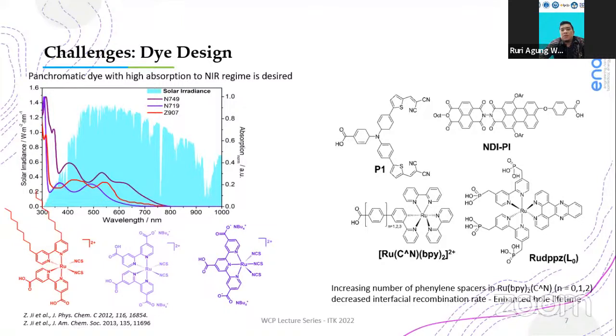In this context, ruthenium complexes or ruthenium polypyridyl complexes are interesting, since the absorption of these complexes in the visible regime is broad and can be further optimized by tuning their ligand characteristics. For P-type dye-sensitized solar cells, the organic push-pull dye is known as the best sensitizer at the moment. However, ruthenium sensitizers can also be optimized by ligand design, stabilizing the ligand-centered radical anion formed upon hole injection away from the nickel oxide surface.